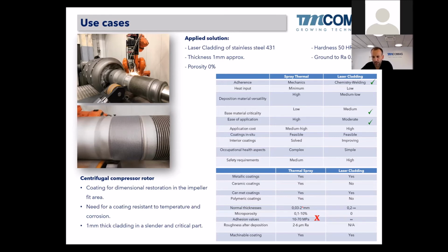chromium, 2% nickel alloy. Thickness about 1 millimeter, 0% porosity. Hardness was not so important, but this coating has a 50 Rockwell C hardness, and then obviously ground to the specific dimension to allow the shrink fit of the impeller in this area. So here we could have sprayed by thermal spray easily, but we considered that as we have to shrink fit a 200 kilo impeller, we need a sound coating perfectly there. So we prefer welding in this case.